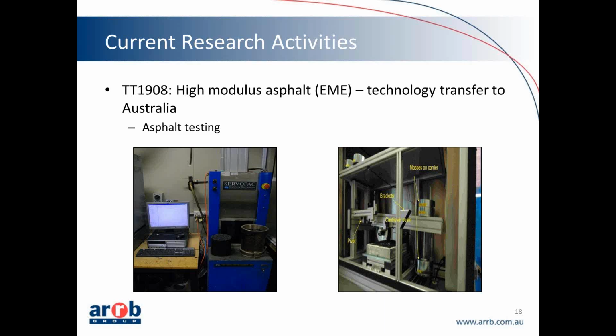But just as a bit of a side note, for the testing that we did here under Australian conditions compared to what the French have done in their test methods, there was quite a good correlation between our results and theirs. So it just basically validated that we could take some French materials, including the bitumen, and do some testing under Australian conditions in an Australian laboratory using Australian test methods and get exactly the same results, or near exactly the results, of what the French could do.